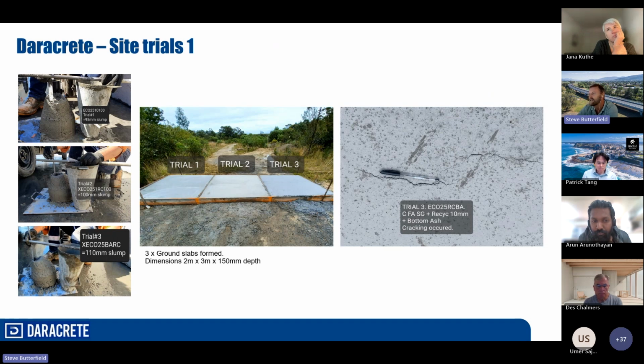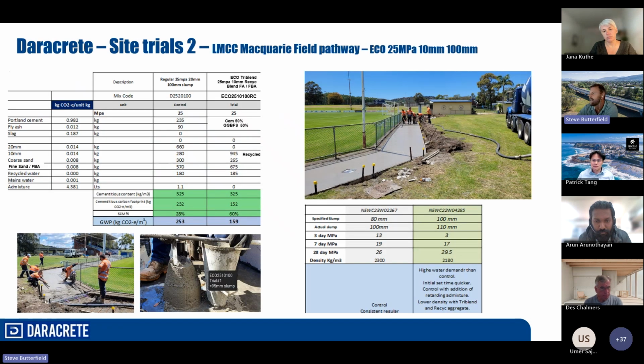You can see on the right hand side there, obviously trial 3 had some substantial cracking early on, which was predicted. That was a really hot day, and we provided no curing for that at all. We're trying to simulate what the residential market is, which I think most guys listening to this will know is pretty rubbish when it comes to curing. So we just wanted to try and match that, see what happened. Obviously, with that amount of slag and that amount of fines in there, water demand was really high.